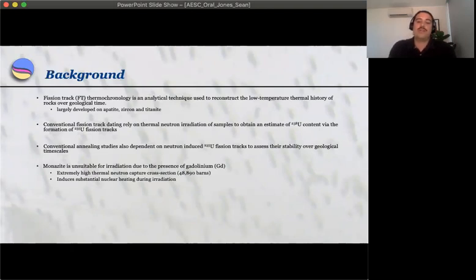These methods have hindered the development of monazite as it is unsuitable for irradiation due to the presence of the rare earth element gadolinium. This is because it has an extremely high thermal neutron capture cross-section of nearly 49,000 barns, which can cause substantial nuclear heating during irradiation and can even melt the grains.